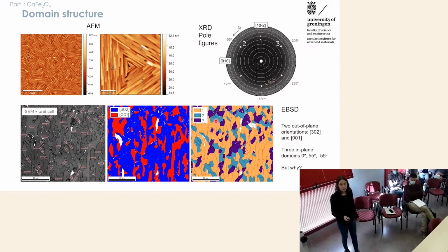And by electron backscattering diffraction, we can actually look at each individual domain and figure out how the crystal is oriented locally. And these are maps that show the out of plane in the first case and the in-plane orientation of the crystals. So it's absolutely clear here that both of the 2 out of plane orientations that correspond to the peak at 33.5 are present. So the film has a mixed out of plane orientation, and each of them comes with these 3 in-plane variants. So there are actually many structural domains in these films. And of course, the first question that came to our mind is, why does this even happen?